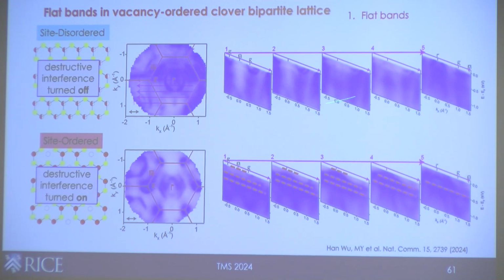And there's actually a way to switch back and forth between these two in a non-volatile way, but I won't. This is because the vacancy order is much more easily switchable than the whole crystal structure. So this is another advantage of constructing these kinds of lattices using vacancy orders.